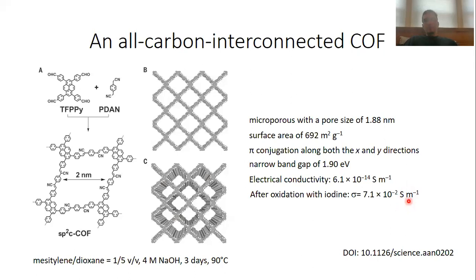So an interesting research direction in this field is to further narrow the band gap and to make all carbon interconnected COFs which are eventually metallically conducting. But to my knowledge, this hasn't been achieved thus far, primarily because no synthetic routes have been found in which you interconnect the building units not by a simple carbon-carbon double bond, but by multiple carbon-carbon double bonds.